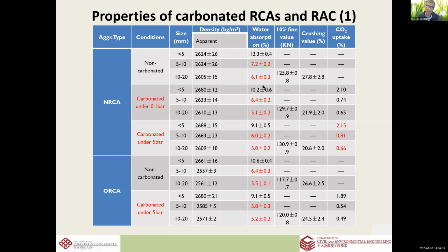Particularly, if higher, this is 0.1 bar pressure, this is 5 bar pressure, and there is some improvement in water absorption that is demonstrated. The 10% value is not just like the crushing value, it's a reverse of the crushing value. With carbonation, there is some improvement in the strength of the aggregate, and there's some CO2 uptake after carbonation.